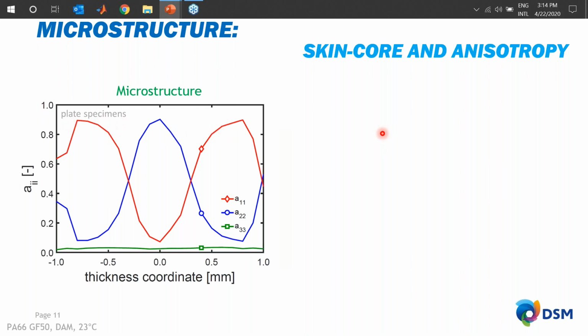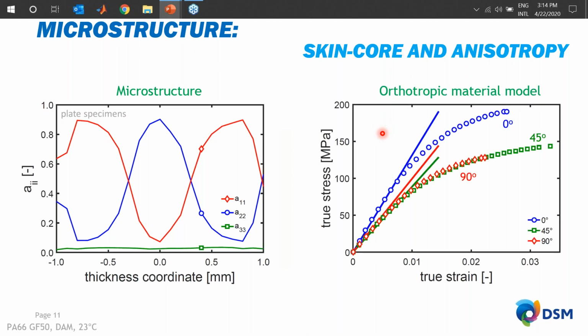So you have to take this into account because as a result of this pronounced skin core structure, you also get a very anisotropic material behavior. So here on the right, you can see the true stress versus the true strain. And you can see that looking at the 0-degree performance and 90-degree performance, the loading direction really matters on how the material performs.